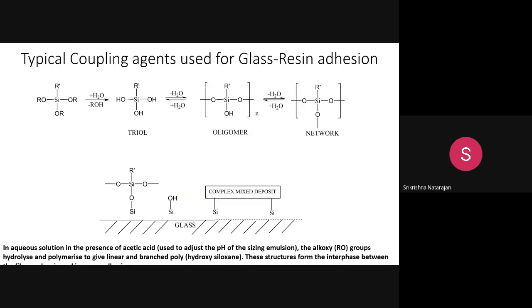Okay, so this is the glass fiber structure. You can see SiO, which is surrounded by 3 oxygen, and R is there. When it undergoes some dehydration or hydration, if you add some water, finally over this glass fiber structure, these coupling agents will form an attachment. It is like a composite where the glass and the resin get attached. In the aqueous solution, in the presence of acetic acid, normally under acidic pH, the glass and the resin undergo this fixation.